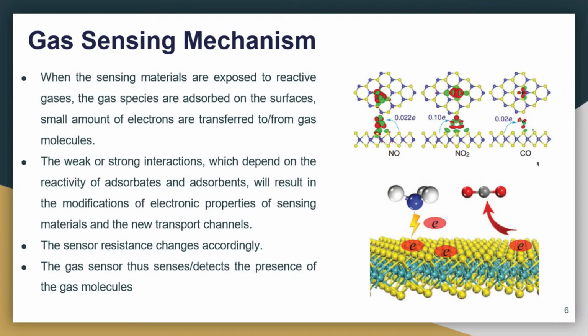and which adsorption site is weaker. So here we can see the electron transfer from the substrate to your gas molecule is around 0.1 electron. But for CO and NO, the charge transfer is around 0.022. So this indicates that there is a significant charge transfer between your two-dimensional material and the gas for NO2. So this material can be used for high sensing applications, particularly for NO2. So these are the important factors we are calculating from the DFT calculations that will give information about the ability, sensitivity and selectivity of your gas sensors, especially for two-dimensional materials.